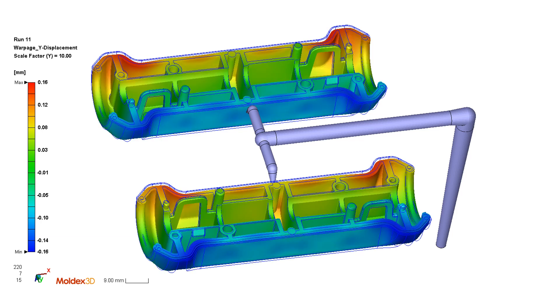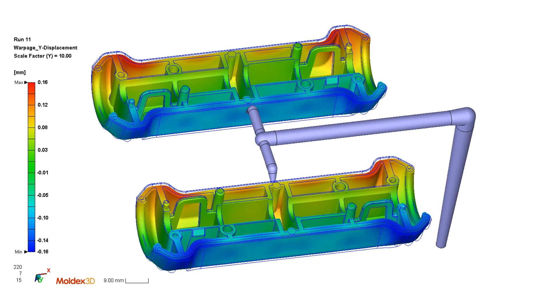Now let's take a look at what happens in the Y direction. The Y direction is the width of the part and you can see blue and red areas and the scale on the left side plus and minus 0.16 millimeters. The really dark blue and really dark red areas shrink inward just a little bit more as the center region where the gate is located. So these sections move in a little bit more than the center and therefore the part warps slightly.